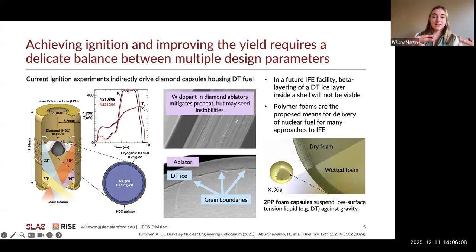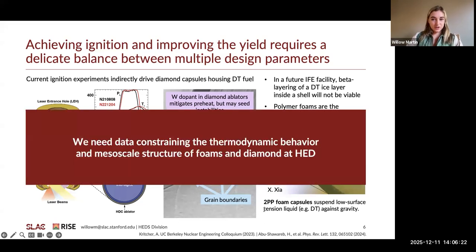These models then get plugged into hydrodynamic simulations to predict their behavior at high energy density. But because of the high computational cost, most foam EOS modeling neglects its microstructure and evolution under shock compression or heating. So it's critical that we acquire data to characterize the homogenization of foam microstructure and its effect on the overall equation of state of the material as a function of time.